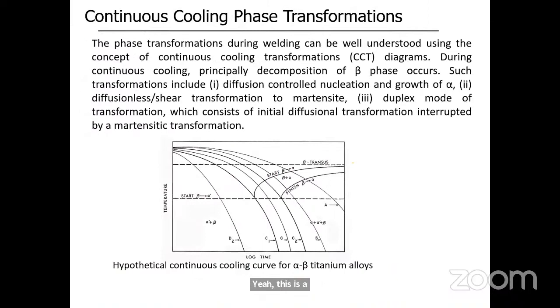Same thing explained here. This is the continuous cooling transformation diagram for alpha beta titanium alloys. Here you can see continuous cooling of alpha beta titanium alloys. This line is the beta to alpha transus temperature, and this is the finish of the beta to alpha transformation, and in between you can see alpha plus beta and different cooling rates. So during continuous cooling, what will happen? Principally, decomposition of beta occurs, so diffusion controlled transformations like nucleation and growth of alpha will take place. If you quench fast, like these fast cooling curves, then you will get a diffusionless or shear transformation to martensite. Or sometimes, if it is in between, you will get a mixed mode of transformation. That is, the initial transformation is diffusional, then it is interrupted by martensitic transformation.